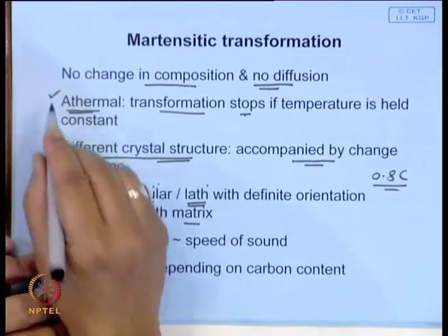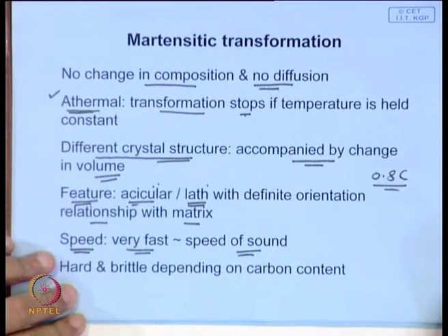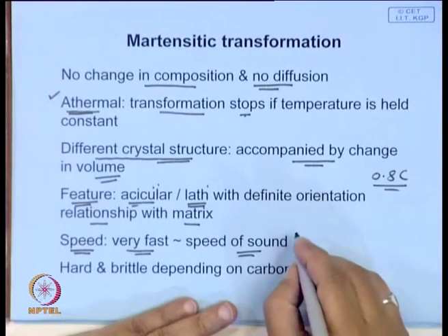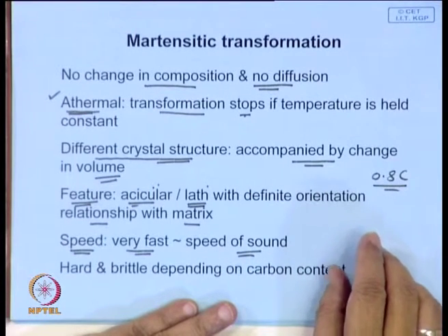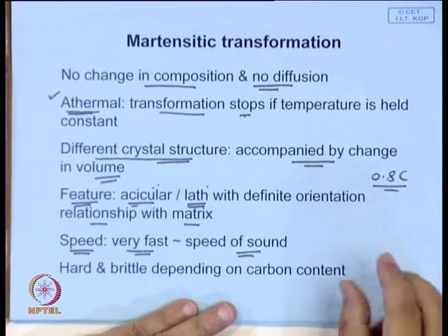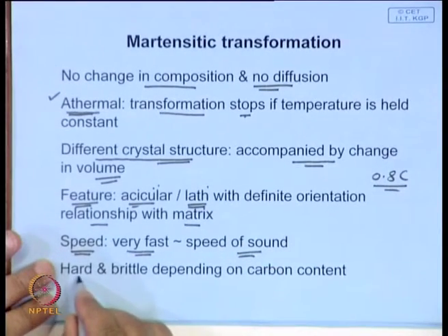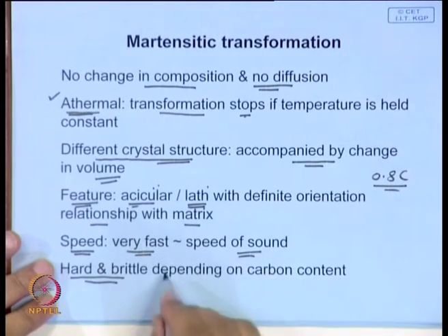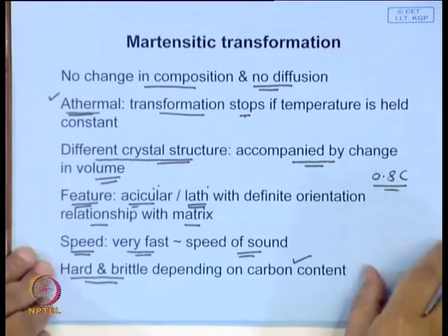So, that is the athermal character, and the speed is of the order of sound. That means the front moves at the speed of sound. Therefore, when the martensite forms, if it is possible to keep a microphone, you can amplify and hear the noise. And since you are keeping so much carbon in solution by force, it is extremely hard and also brittle, and this extent of hardness and brittleness will depend on the carbon content it has.